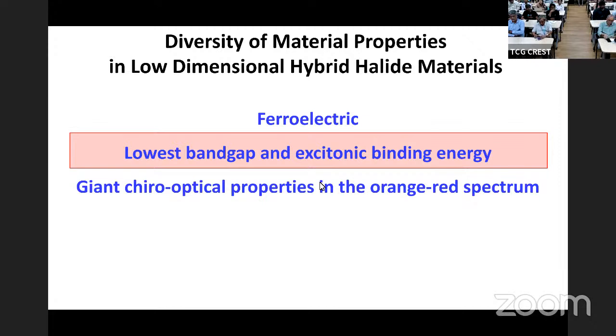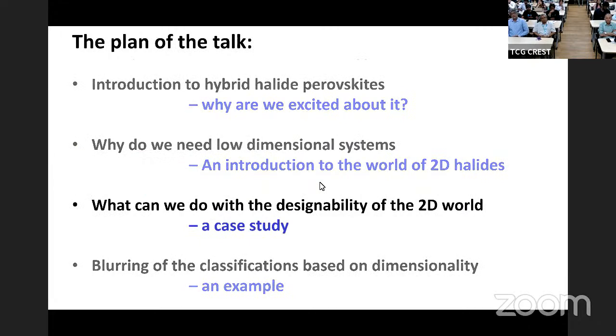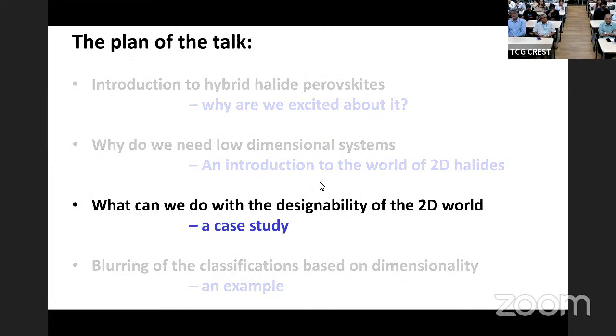It turns out that we have been able to get a material that has the lowest band gap and lowest excitonic binding energy while being extremely stable with respect to moisture, one of the highest stabilities in moisture of this class of material. And that's the main story I'm going to talk about. Then later I'll come back to where this strict confinement in terms of dimensionality gets blurred, as I have pointed out. So that brings me to this topic.